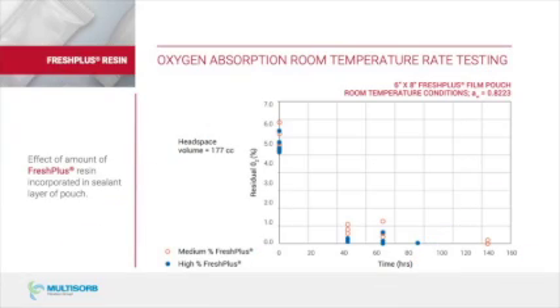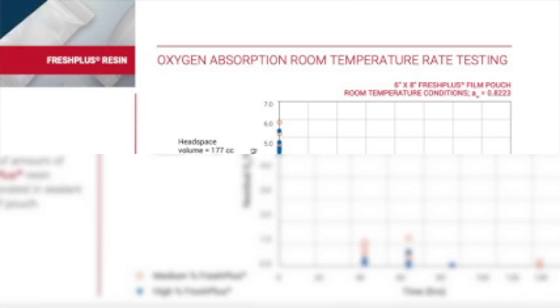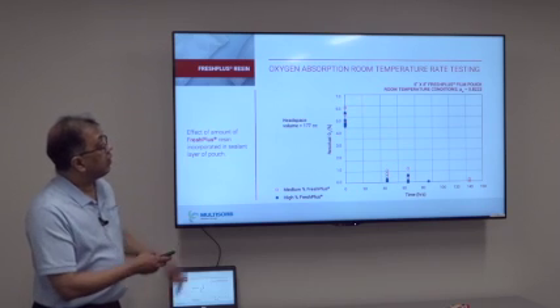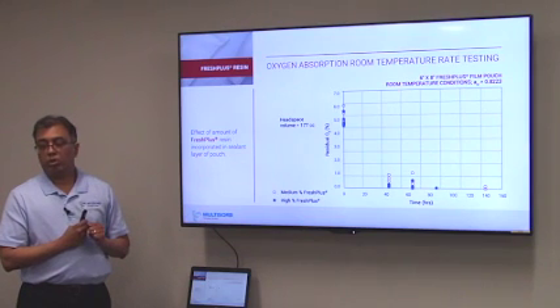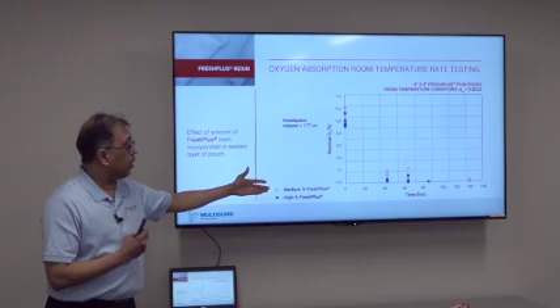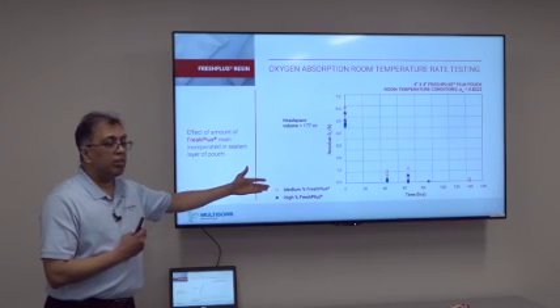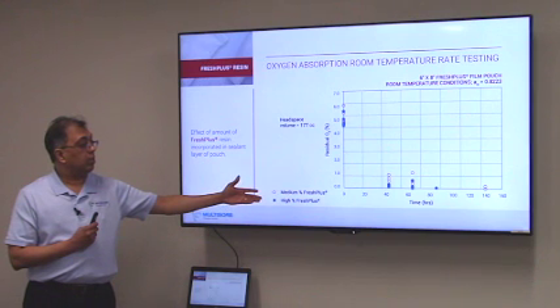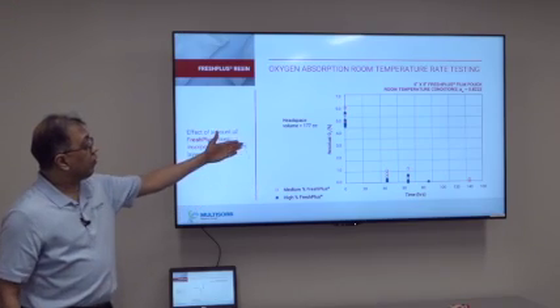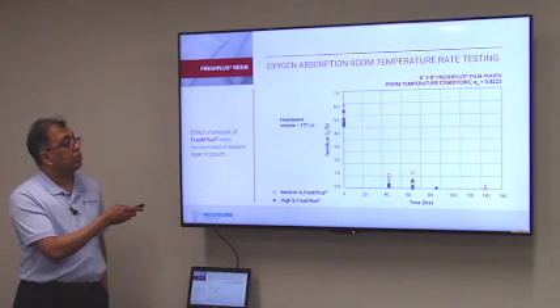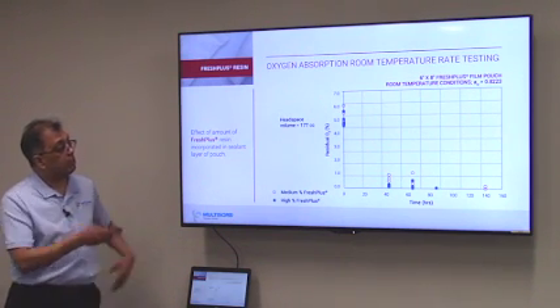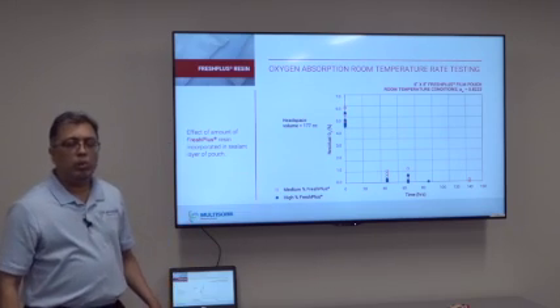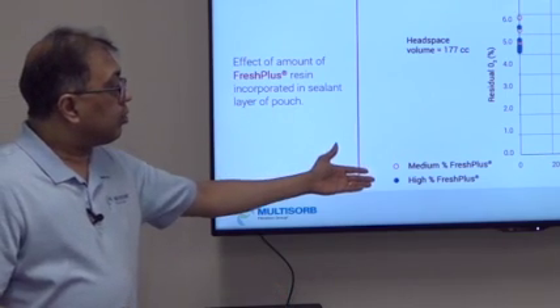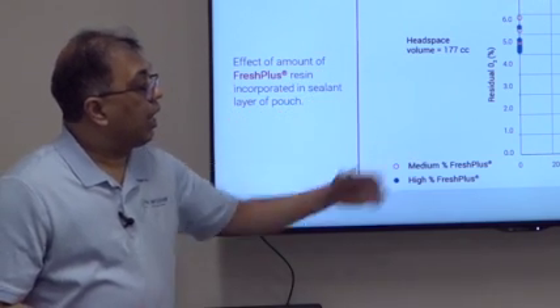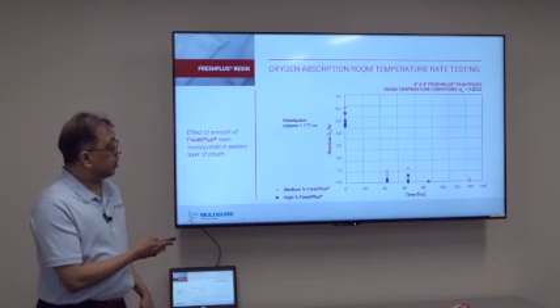This graph shows the residual oxygen as a function of time after we package meat snacks of water activity 0.8 in a 6x8 Fresh Plus film pouch. We have used two design variables. One is a medium percentage of Fresh Plus in the sealant film and the other a high percentage of Fresh Plus in the sealant film. And what we observe is, even at starting residual oxygen concentrations of 6%, we have been able to reduce it to 0 within 6 days. The higher the concentration of Fresh Plus, the faster the rate at which the oxygen is reduced to 0.